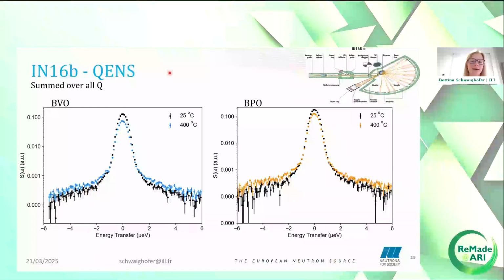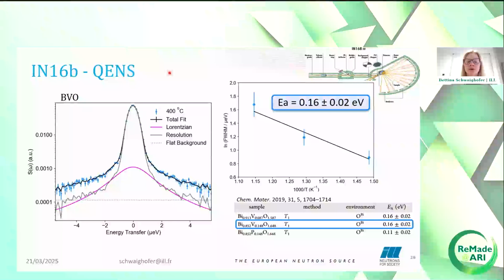But we could still analyze it. The analysis was done, as I mentioned in the introduction, with a convolution of a delta function and the resolution to account for the elastic peak, and a Lorentzian for the broadening. This allows us to obtain the half-width at half maximum of the broadening, and the temperature dependence of this is related to the activation energy which causes the broadening.